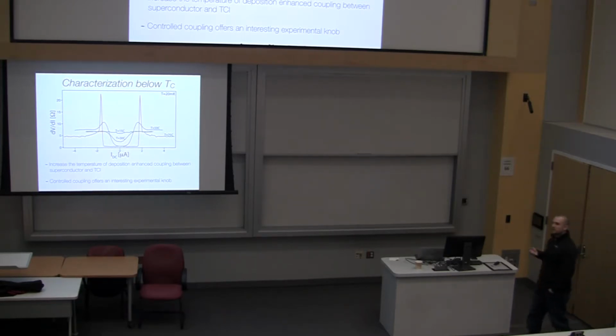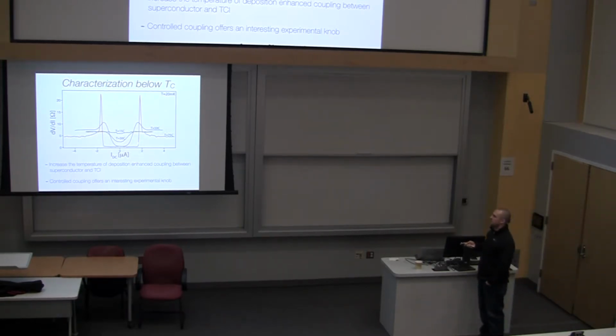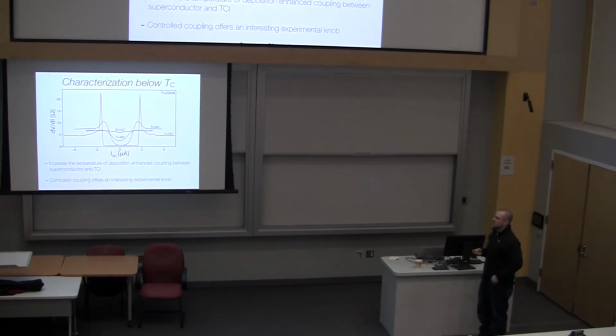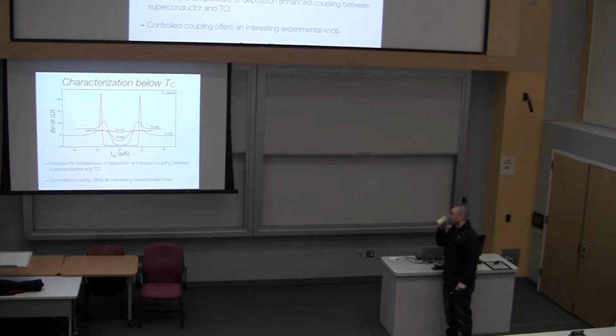At some value of current called the critical current, there's a jump into the normal state. And so you'll see a lot of plots that are dV/dI versus this I_DC. And these peaks in dV/dI indicate the position at which the device goes normal, which we call the critical current.